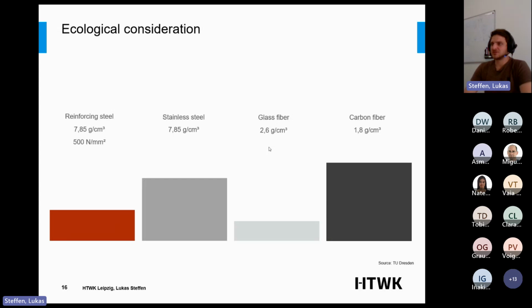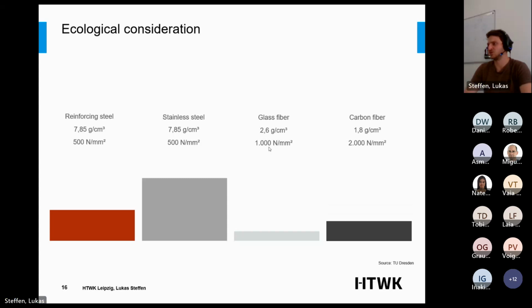If you take into consideration the tensile strength, for reinforcing steel it's 500 Newton per square millimeter. For glass fiber, it's 1000 Newton per square millimeter, so you halve your use of the reinforcement. And for carbon fiber, it's 2000 Newton per square millimeter. Therefore, you only need 1/4 of the carbon fiber compared to reinforcing steel. If you use high performance carbon fiber, it's like 4000 Newton per square millimeter, and you halve it again. So if we consider this, we have more than 50% reduction of the CO2 emissions in the reinforcement for our carbon concrete.